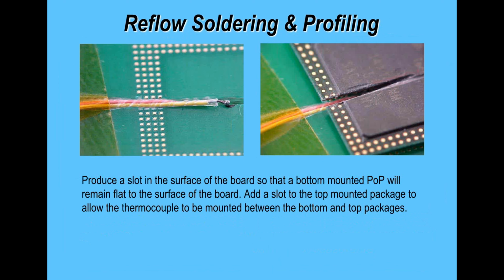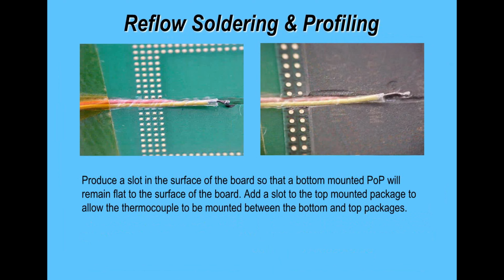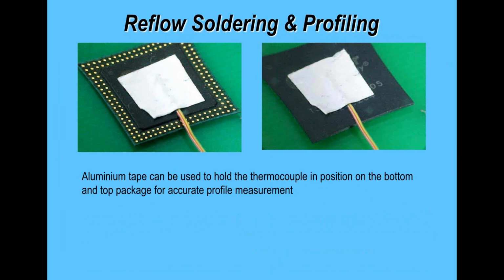Now if you're going to be monitoring under package-on-package POP devices, I wanted to show you a technique that I use. I'm not saying it's perfect, but it works quite nicely for me. And here what I've done is I've routed the board. This allows me to use a thermocouple which is slightly thicker, hence it's going to last and be less prone to damage, and position the thermocouple underneath the POP package. I've also routed the bottom POP package, which again allows me to mount a thermocouple into that and then mount the POP package on top, thus monitoring on the board, underneath one package, and then possibly on the top package, as you see in these examples.